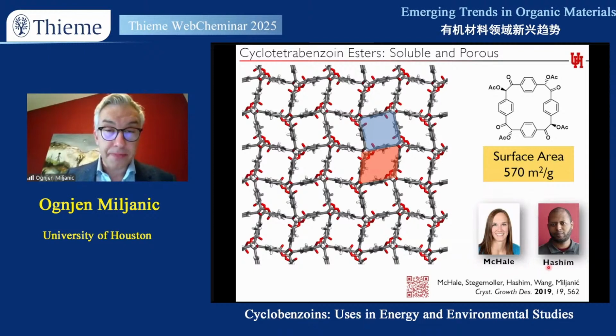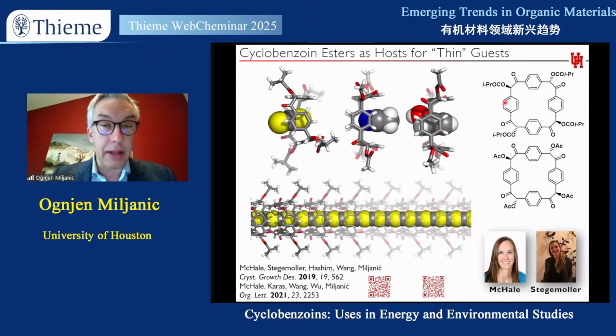Now, with linear pi electron-rich guests in the pore of this cavity, what we see here on the left are crystal structures with carbon disulfide, a linear molecule, acetonitrile, where you see the triple bond of acetonitrile sort of timidly protruding into the cavity, as well as propargyl alcohol, where again you see the terminal CC triple bond included in the cavity here. Now, to be completely open about this, this is related to the solid state. So in solution, we are still not even able to see this binding. So it seems to be relatively weak.